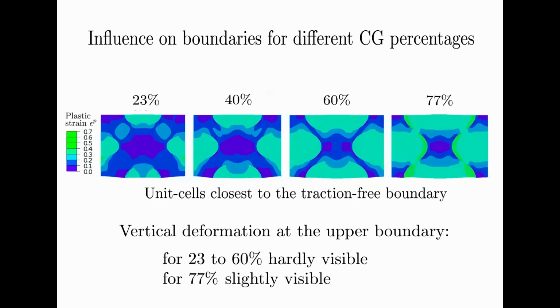So that's that part. Also, when we looked closer at this, this is a unit cell. So here you have the coarse grain and coarse grain and coarse grain and coarse grain, and the rest is skeleton here. And this shows the plastic deformation, plastic straining. The thing that struck me when my student came back with it was that you get this curvy. This is the lowest part of the model part. You see it's curvy because of loss of tractions. This is traction free, so it bulges out as it wishes.